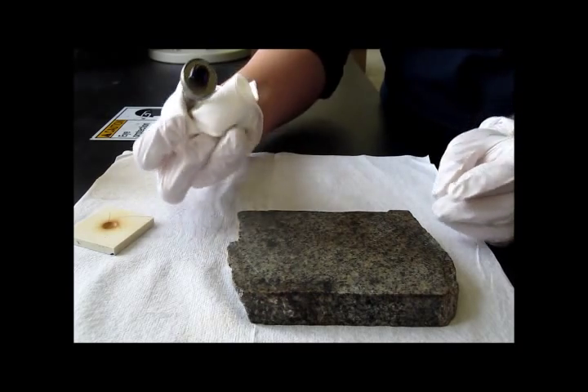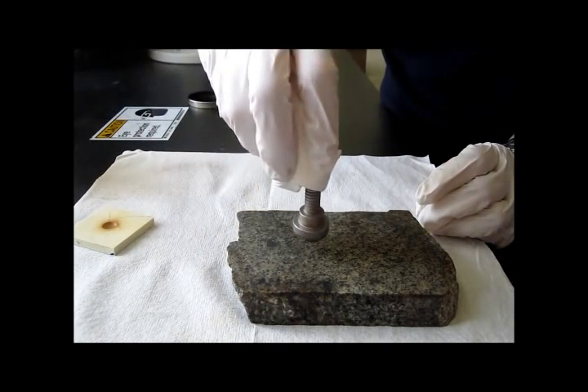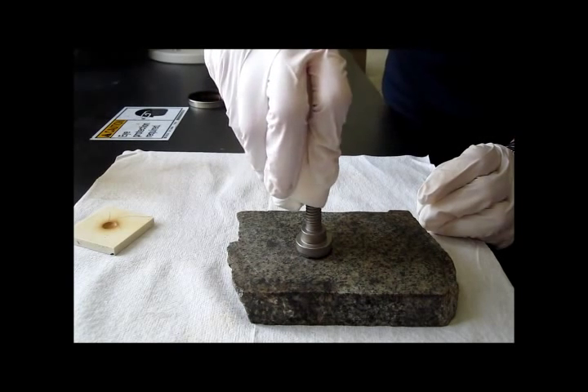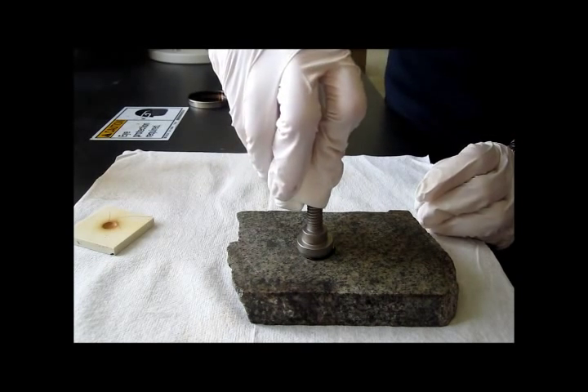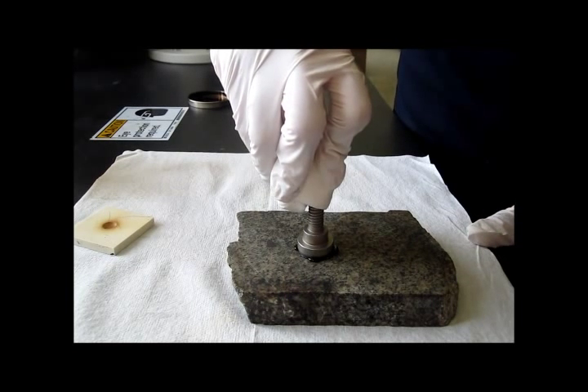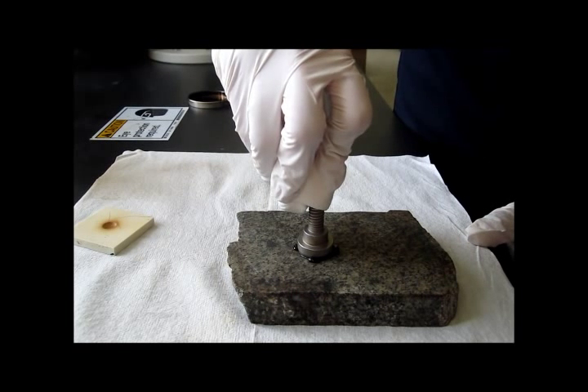The stubs need to be pushed down as straight as possible and twisting needs to be avoided to reduce the formation of trapped air bubbles inside the sample and to minimize stresses. Position binder samples on the substrate to allow for placement of multiple applications and for sufficient clearance of the testing apparatus.